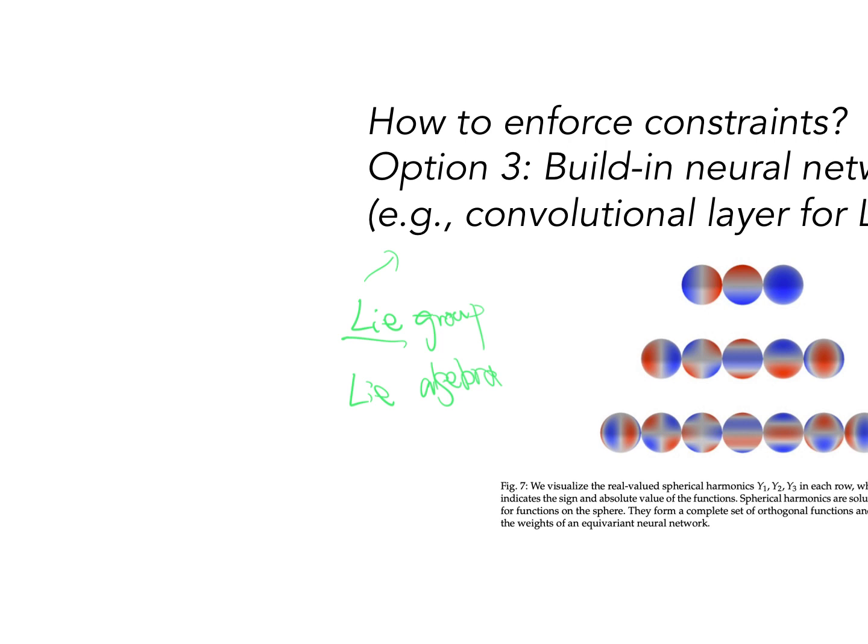One way is that if you have symmetry, in particular if you have isotropy, then you can inherently build in something that is invariant to the rotations, because you can predict epsilon 1, epsilon 2, epsilon 3 to sigma 1, sigma 2, sigma 3. This is one choice, right? Why would that work for SO3? Because no matter how you rotate your frame, you have the same eigenvalues.